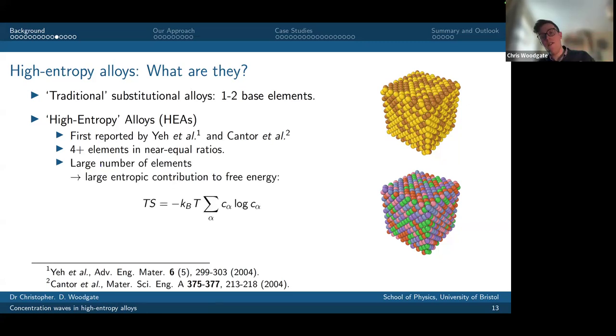Okay, and it turns out that if you write down a toy model of your free energy, this large number of elements present in the composition means that you have a large entropic contribution to the free energy. So TS here, this is the entropic term in my free energy. Boltzmann constant, temperature, and then a sum over alpha, a chemical species. C alpha is the overall concentration of each chemical species. And the sum over alpha, C alpha log C alpha, gets larger as the sum runs over a large number of elements at lower concentrations. And so there are certain combinations of elements where this entropic term is perceived to help to stabilize a single phase solid solution that might not otherwise form.